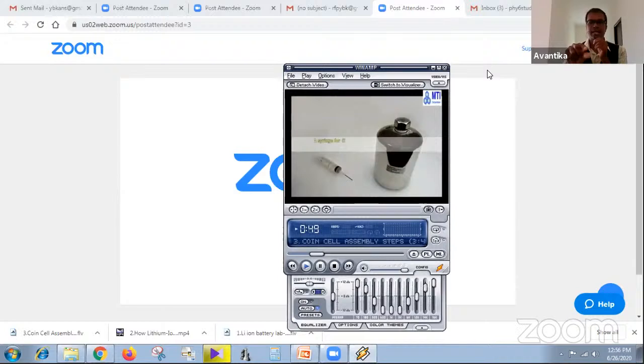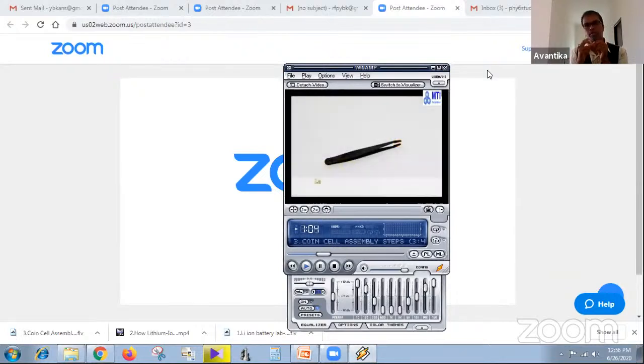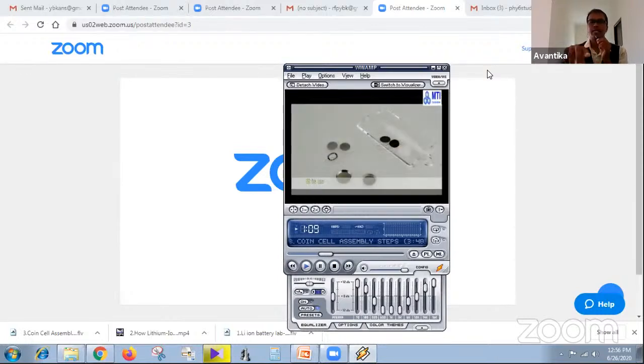So this is the electrolyte. Generally, in the laboratory, they use lithium hexafluorophosphate as the electrolyte. In the chemistry lab, they are also optimizing the electrolyte in order to improve the performance of the battery. Once you prepare the cathode material, we have to optimize the material, and after optimization, we have to coat it on the aluminum foil and keep it for the assembling of the coin cell.